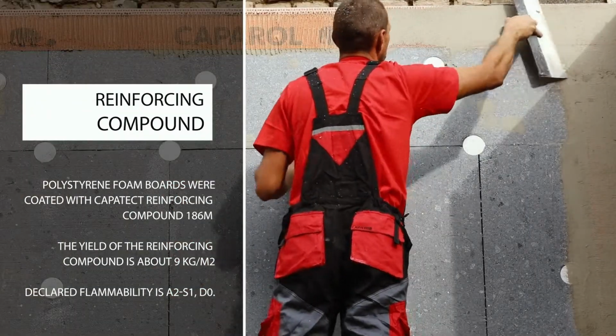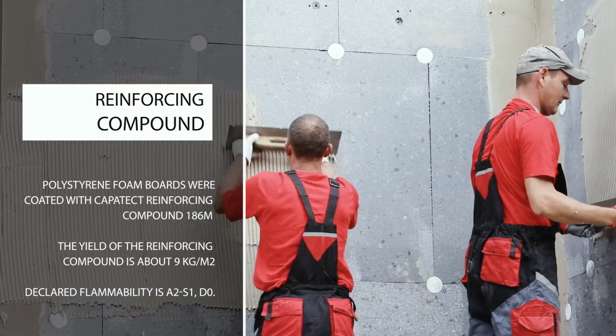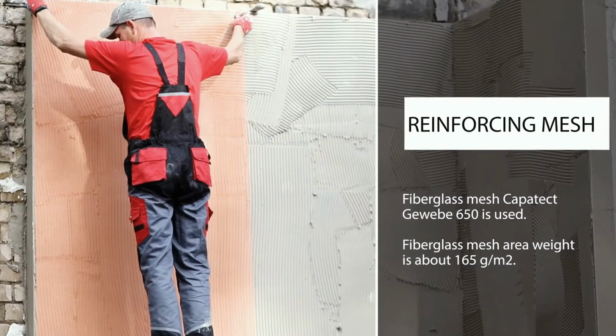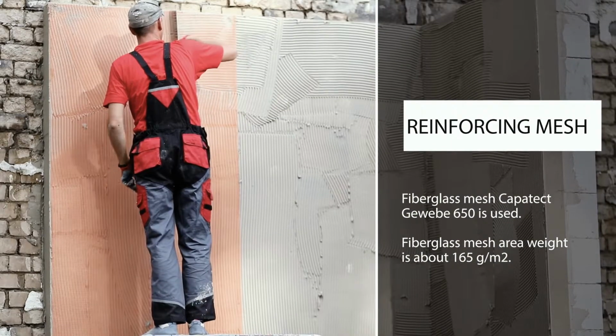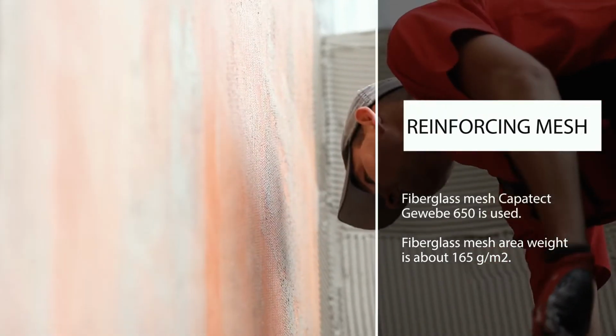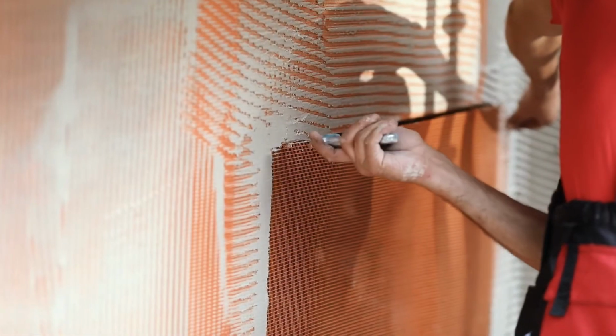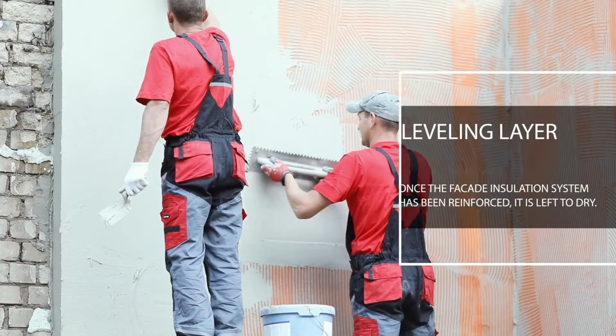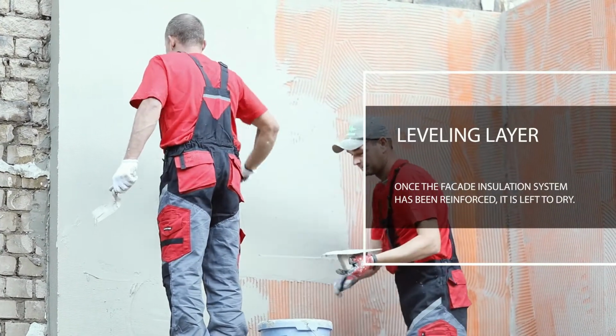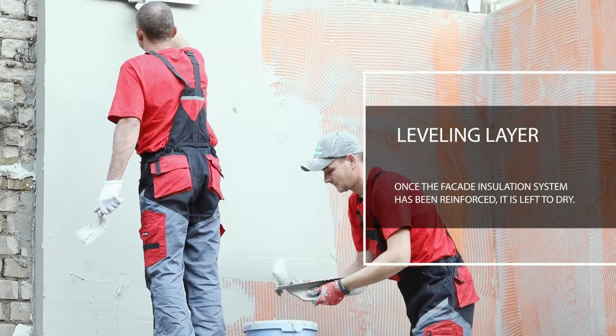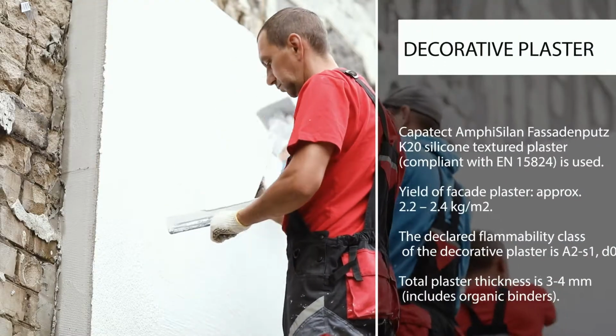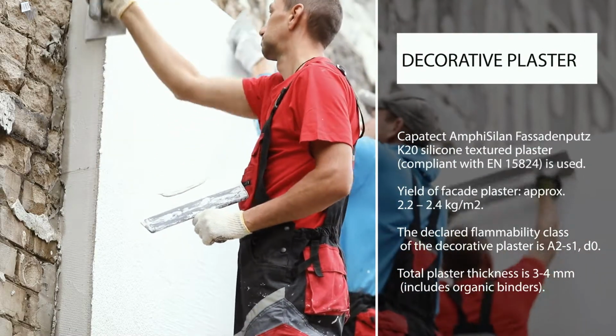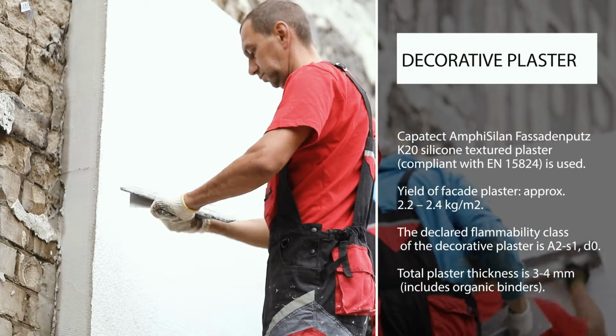The yield of the reinforcing compound is about 9 kilograms per square meter. Capatect fiberglass mesh is used for reinforcement. Fiberglass mesh weight is about 165 grams per square meter. Once the facade insulation system has been reinforced, it is left to dry. Once it has dried, the facade finish is installed using Capatect silicone textured plaster.